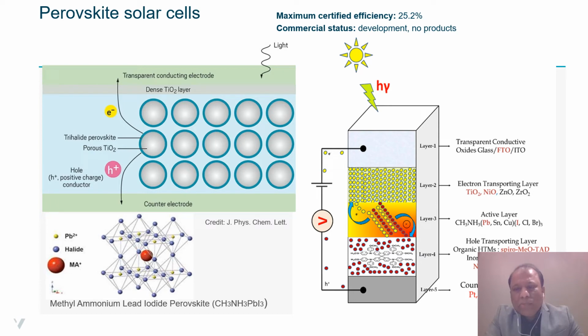So here we can use a lot of materials for the electron transporting layer. We can use titanium oxide, and we can use SnO2. I'm sorry, it is not shown here, but we can use SnO2. The active layer, of course, will be perovskite. It's the absorption layer, and you have the hole transporting layer. Here, of course, we could use Spiro. That is the most used one, but the thing is, it's very expensive. So people are trying to use inorganic materials, and even carbon-based materials. And you have the counter electrode, that is platinum. Mostly gold is used.